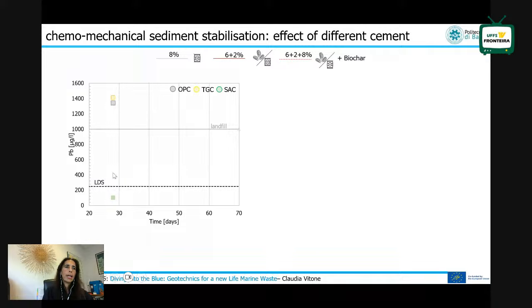In gray, the ordinary Portland, and this is the sulfo-aluminate. As you can see here, this is the effect of the addition of mussel shell powder to our mixture. So if we add mussel shell powder and we reduce the content of cement, we have a reduction of lead. So the mussel shell powder is entrapping lead again for all the cements, essentially. With curing time, if we wait until 60 days, the Portland is also working very well with shell powder, but we have also an efficacy that is boosted if we add biochar.